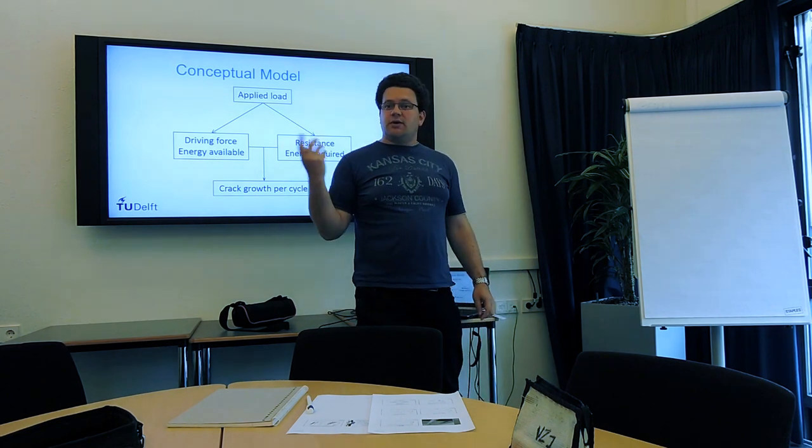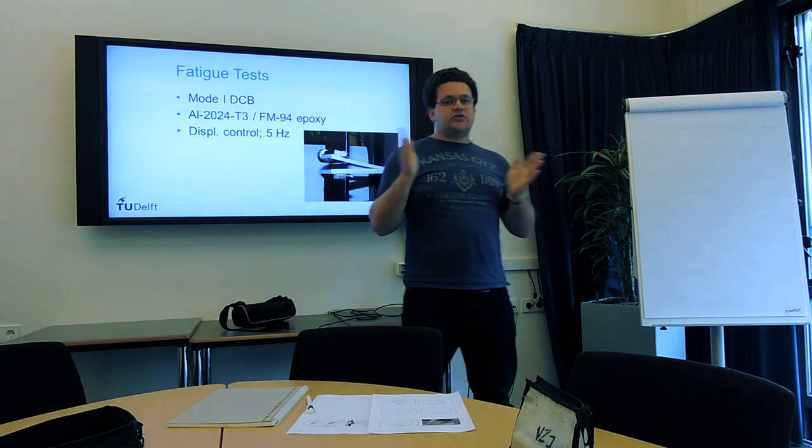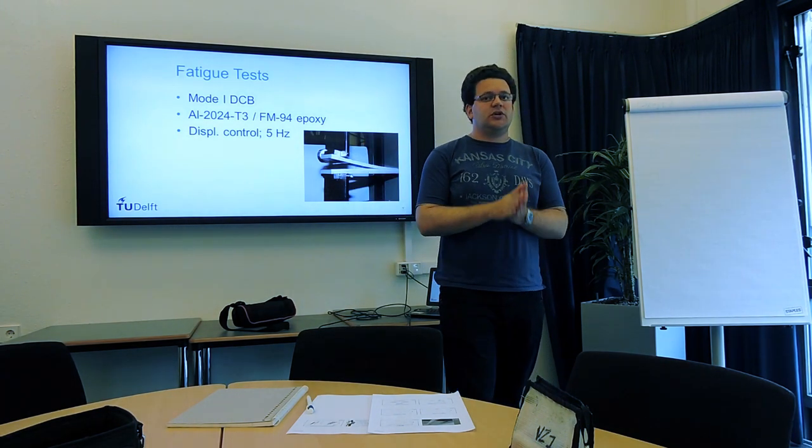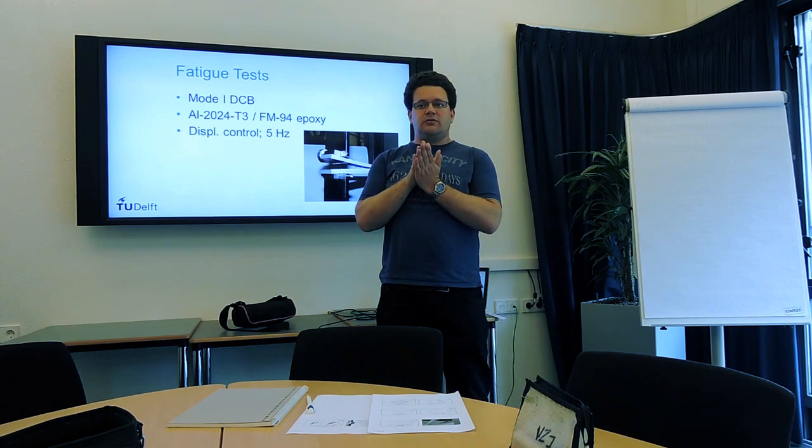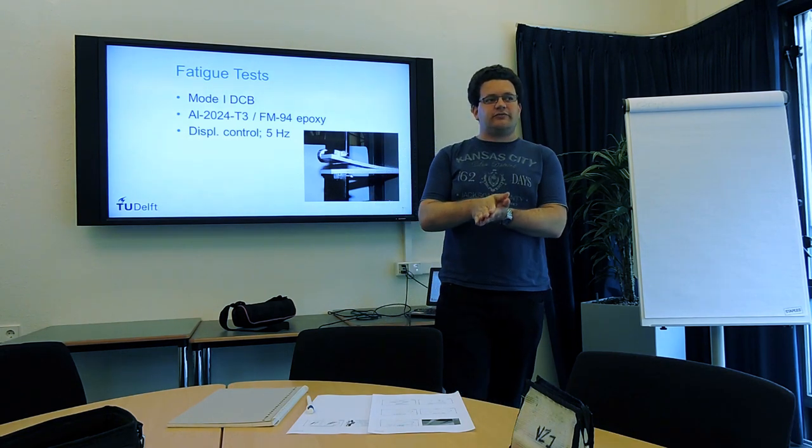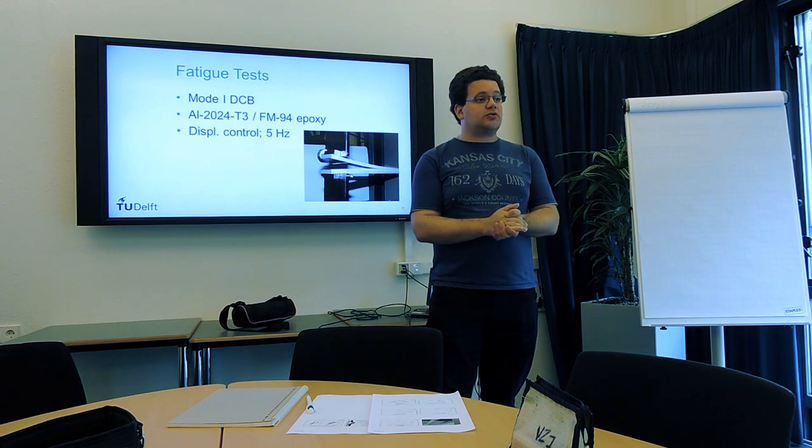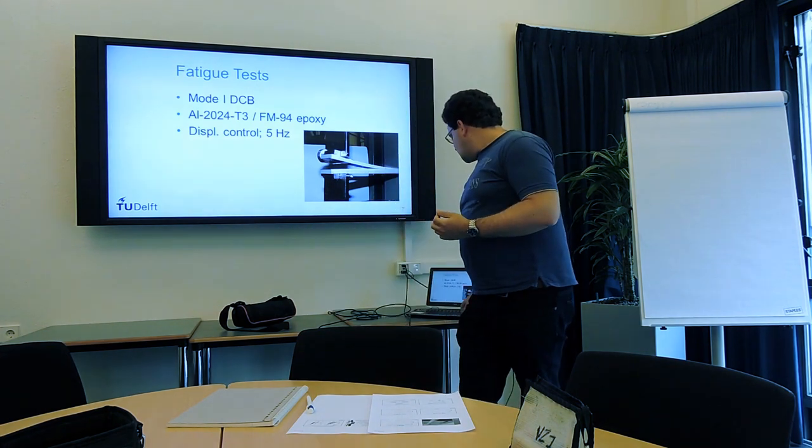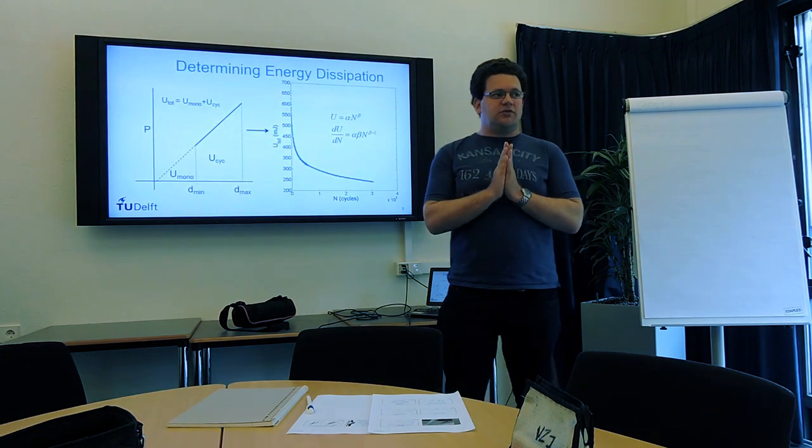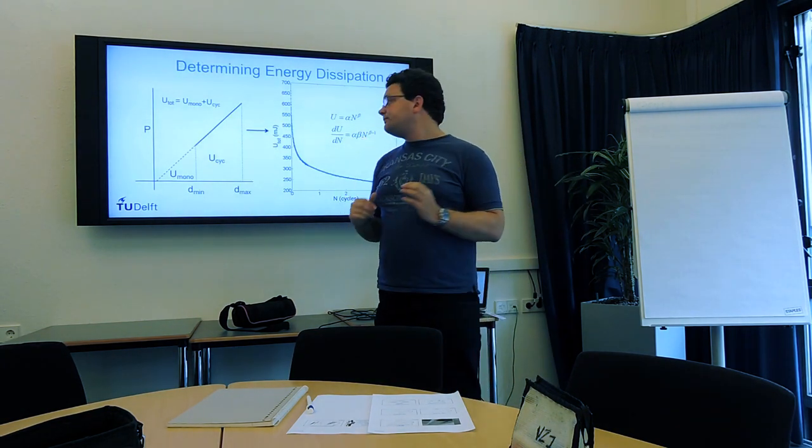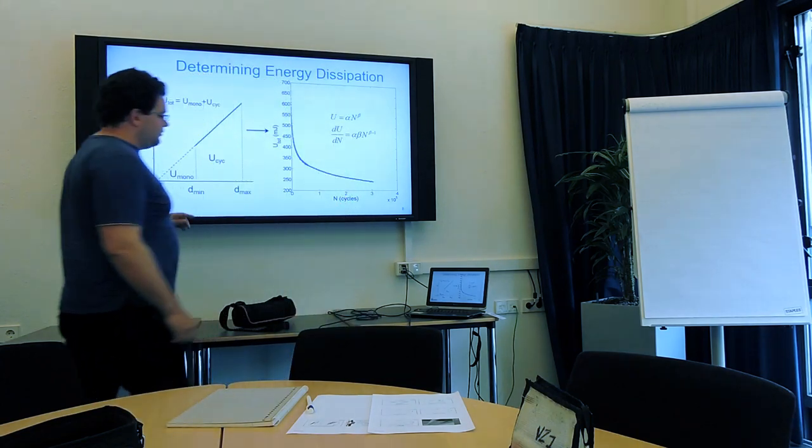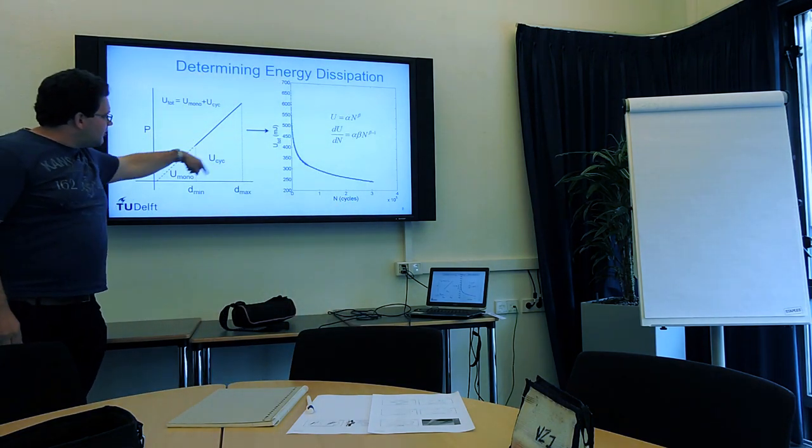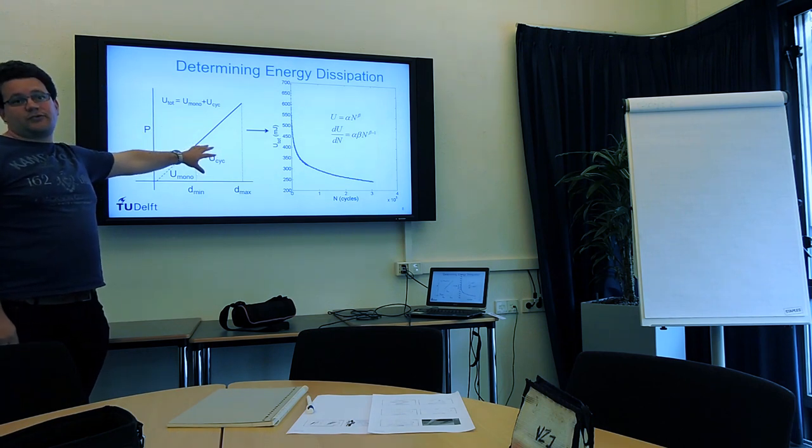So we did some experiments to test this model. Basically, just really simple fatigue tests. Mode one, double-cantilever beam specimens. Aluminum to aluminum with an epoxy adhesive to make an adhesive bond. Mode one opening under displacement control at five hertz. And then what you can do is, when you do the test, the specimens are linear elastic. So if you draw the force displacement line, you get this line. And the area under that line is, of course, the energy in the system.